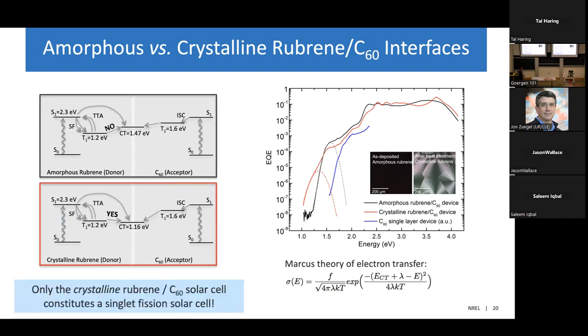So the key takeaway from this study was that even though we have 2 devices that have exactly the same constituent materials, exactly the same layer structure, just because of this morphology difference at the interface, only the crystalline rubrene C60 solar cell actually functions as a singlet fission solar cell. And I think at the time, this was not widely appreciated by the community.